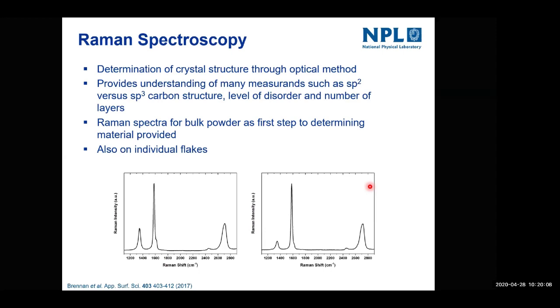And what you get out quite quickly, if you look at the spectra below, is that we've got sp2 hybridized carbon. We're seeing there's some disorder in there, but generally it's a graphitic material. From this technique, you can pull out measurands such as the sp2 versus sp3 content, the level of disorder or defects, and also the number of layers. However, there's a big caveat: because it tells you many things, you have to be careful how you interpret the data. Taking a black box of material and just doing the measurement isn't necessarily going to give you the understanding that you need, hence why we talk about complementary techniques.